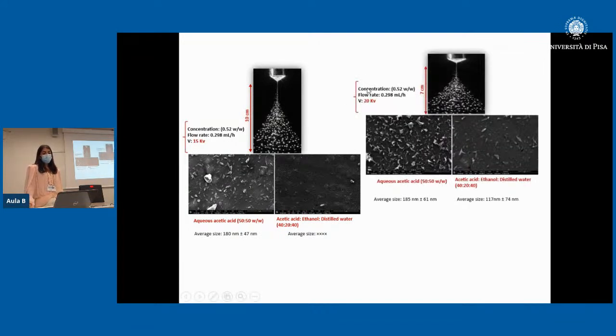So we changed by using the same solvents. We changed the parameters of the electrospray technique, and we used higher voltage, and also we decreased the distance between the tip of the needle and the collector. And in this way, in this new condition, we could successfully produce chitin nanofibrils even using ethanol as solvent. So this shows how important the electrospinning parameters are to optimize and reach the desirable product.